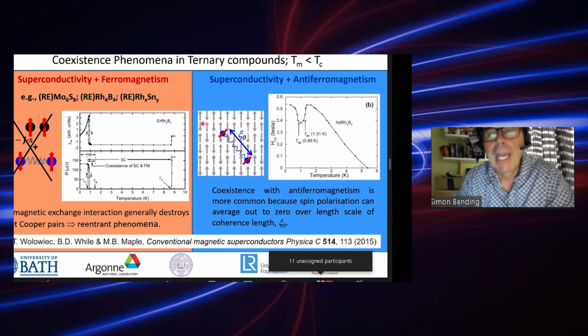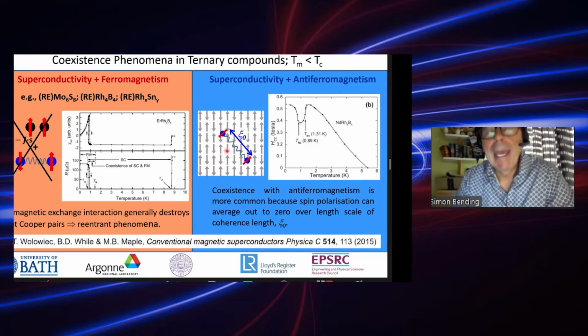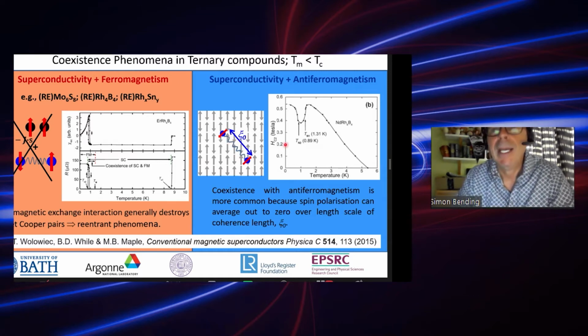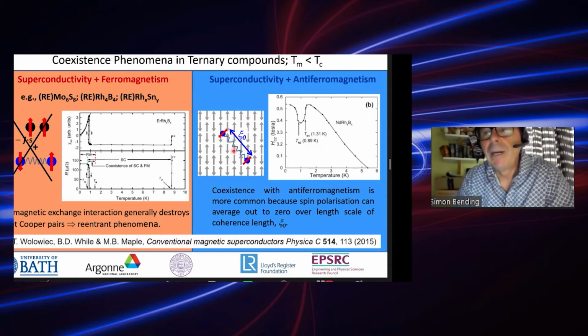If you consider a Cooper pair with a relatively long coherence length, then the pair is actually averaging out over the spin polarization of many of these antiferromagnetically ordered spins, and in doing so they sort of average out the net exchange interaction to something close to zero. So it's much more likely to interact and exist with an antiferromagnetic system than a ferromagnetic system.